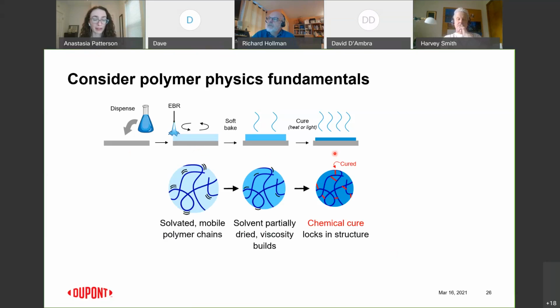So again, we're thinking about cracking. We're thinking about what's actually happening physically with these polymer chains. In this, when it's first dispensed, they're very solvated and mobile. And then at the soft bake step, a lot of the solvent's driven off. And so we get viscosity building and much less polymer chain mobility. And then after the chemical cure, that's when the structure is locked in. That's when the crosslinker activates.